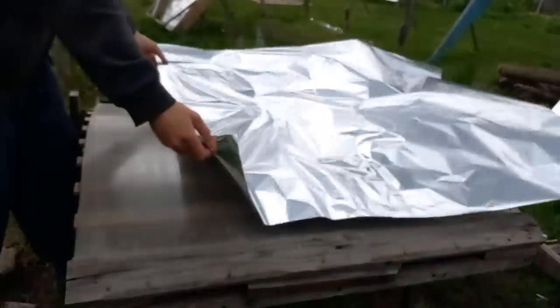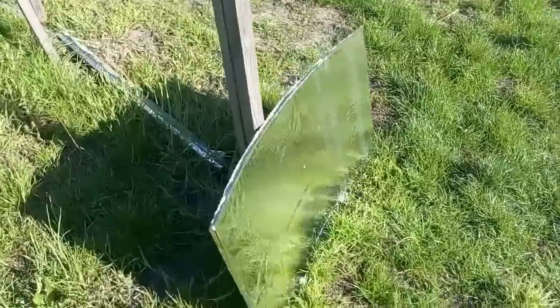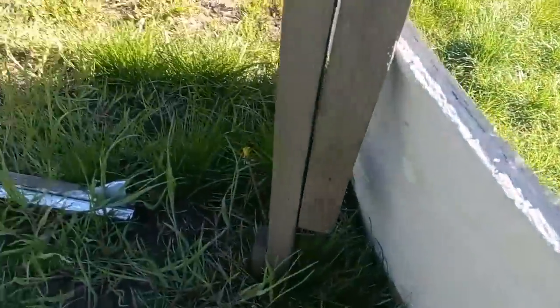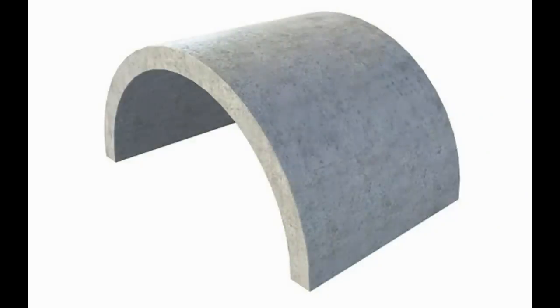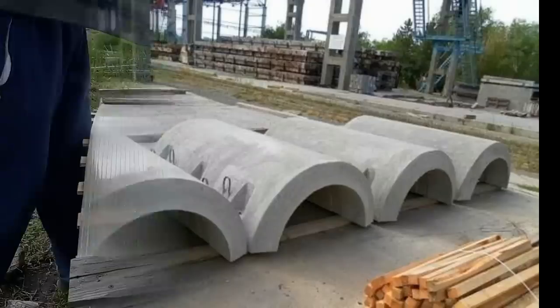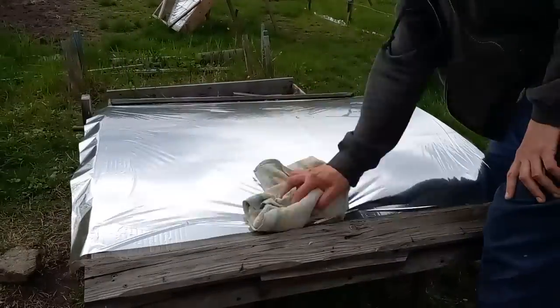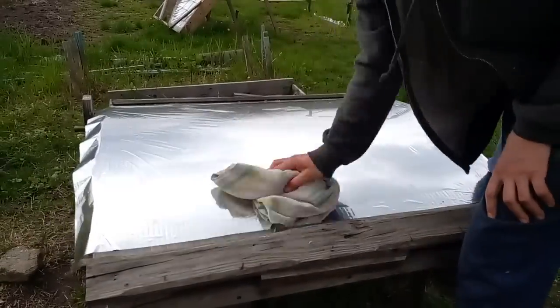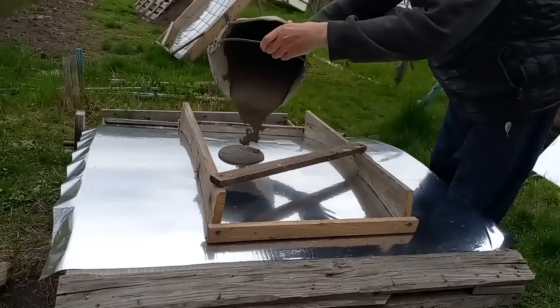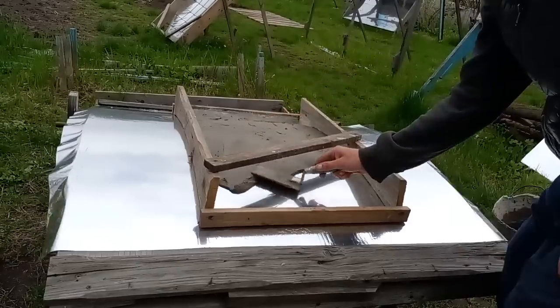Let's look at how I made my mirrors by hand, although we understand that we should have automated production of concrete mirrors, similar to factories for well-known concrete products. The making of my mirrors began with this reflective film, which was temporarily fixed with moisture on a curved surface. Then I put the first layer of concrete, composed of sand with a large proportion of cement.